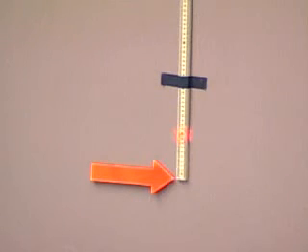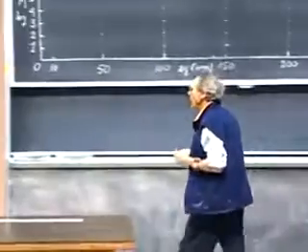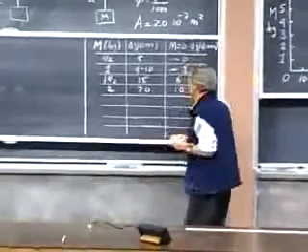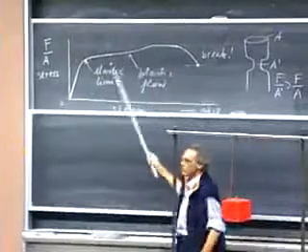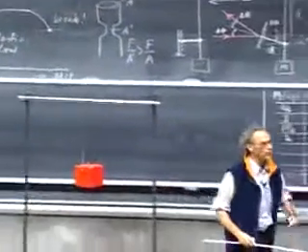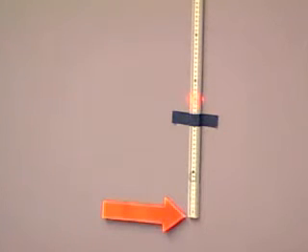So can you remove the 2 kilograms? Oh boy, look at that. There's clear deformation now. It no longer returns to 0, and it's comfortably 10 centimeters long now. So can you make it 2.5? You're now slowly approaching the part that I hope you were going to see, and that is that it's going to take off like a rocket. With a little bit of extra weight, it will start to move substantially. We haven't reached that point yet, but we're close to it. We're now at 25, 26. Still looks quite linear.